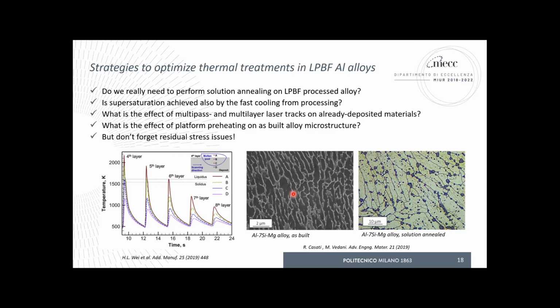Then, is supersaturation achieved during fast cooling from processing enough for promoting dispersion strengthening mechanism during the following aging? So can we skip, in other terms, the solution annealing treatment? I will show you something about that. What is the effect of multipass and multi-layer laser track on already deposited material? We should consider that the deposited material during the additive manufacturing process is not feeling just one thermal cycle, but it will be feeling many thermal cycles corresponding to the different laser tracks.